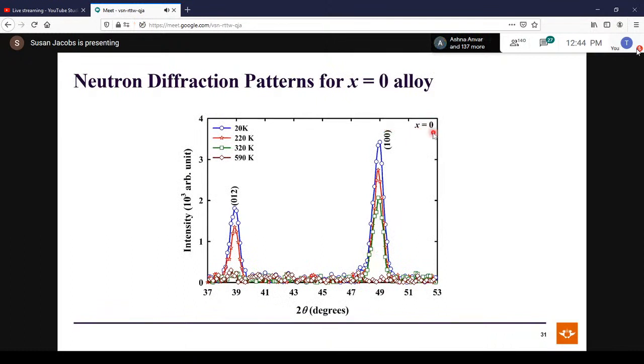This is the neutron diffraction pattern for the x equals 0 alloy. We see the main 100 magnetic peak, which is suppressed as expected as temperature increases. So as you go from 20 Kelvin to 590 Kelvin, the size of this peak decreases and magnetization is suppressed at 590 Kelvin. We don't see any satellite peaks. And if you just see the main 100 peak, the main magnetic peak, it suggests that your alloy is commensurate. So this x equals 0 alloy is in the commensurate spin density wave phase.